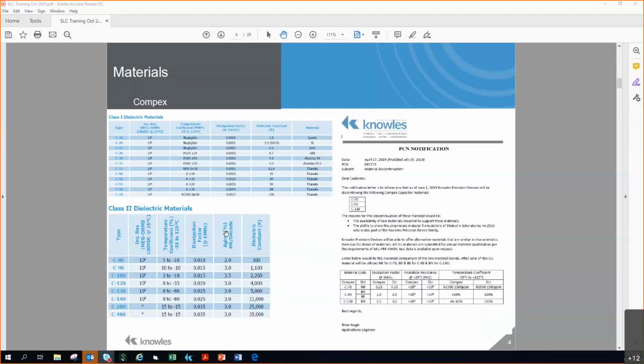The one that you don't see on the DLI side that you will see on Compex is the C400. That's a 35,000 K dielectric. Everything else is pretty much similar or the same. We don't offer that on the DLI side, but it is something that we offer on the Compex side, and it really has to do with the firing and sintering stages within the C200. It's very similar to that process, just to get the K up.